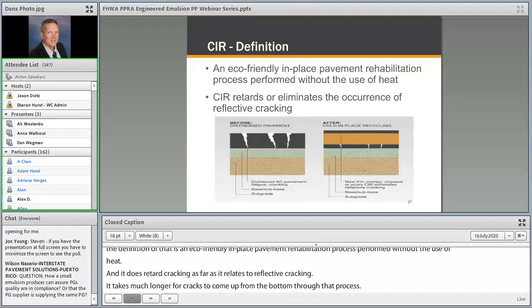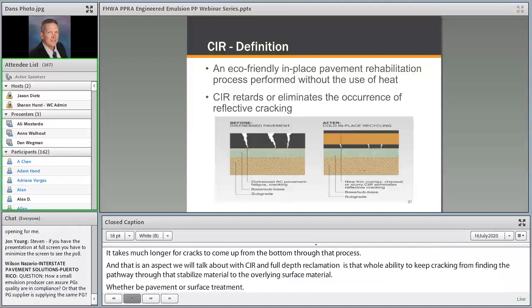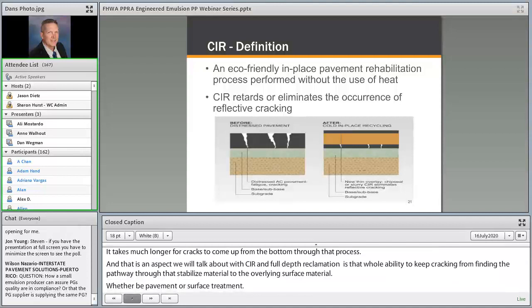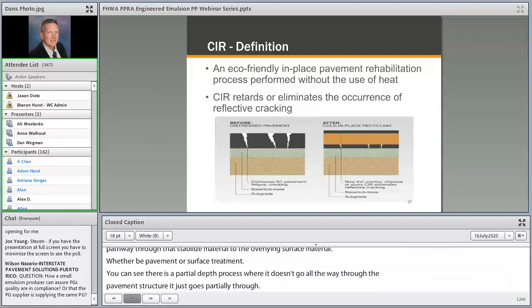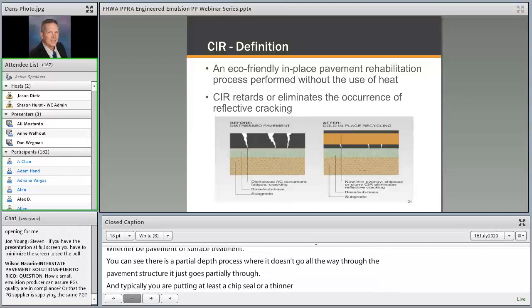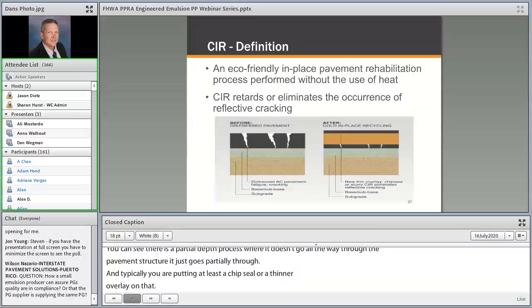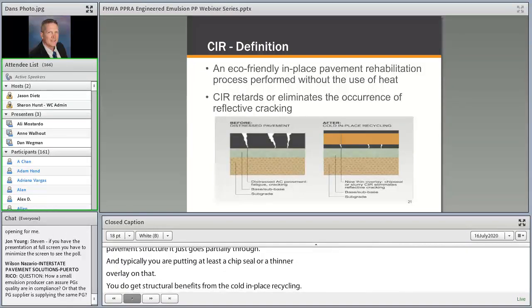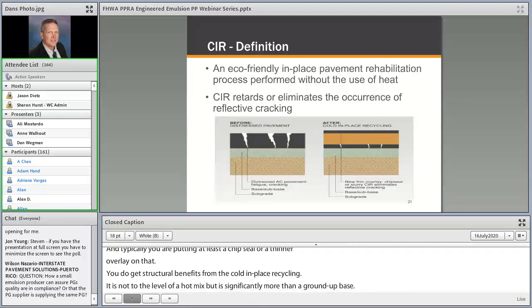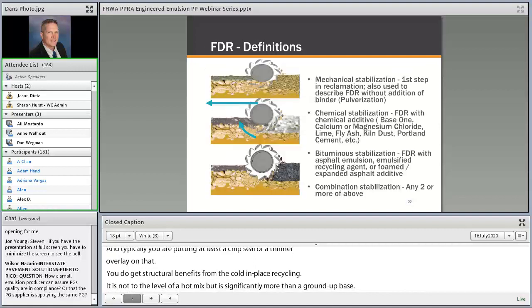As you can see here, it is a partial depth process where it doesn't go all the way through the pavement structure. It just goes partially through, and typically you're putting at least a chip seal or a thinner overlay on that. You do get structural benefits from the cold in place recycling. It's not to the level of a hot mix, but it is significantly more than a ground up base, and you can utilize that in terms of reducing your overlay thickness, which makes the whole process more economical in the overall picture of it.